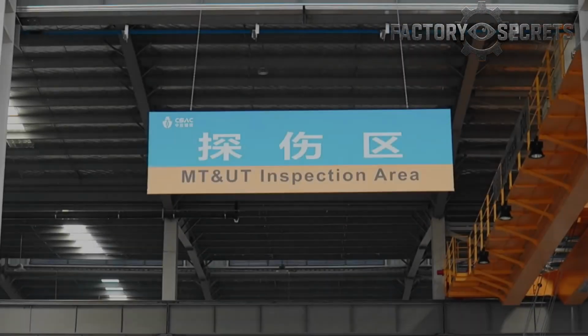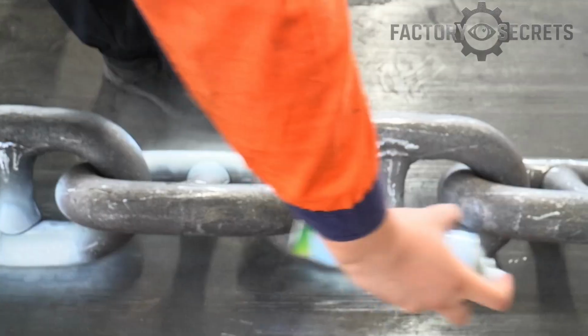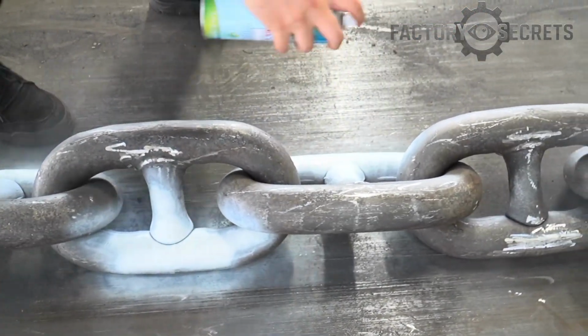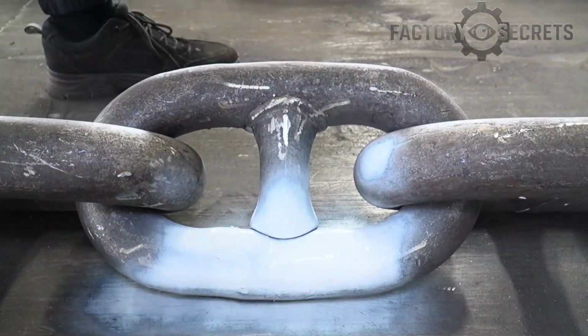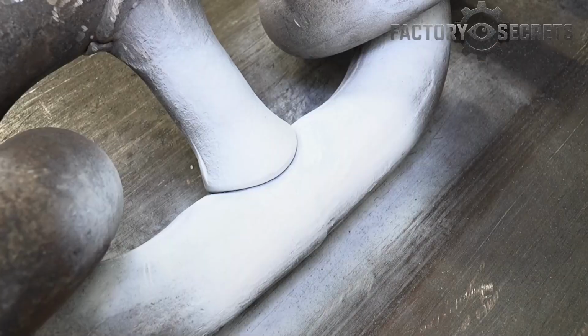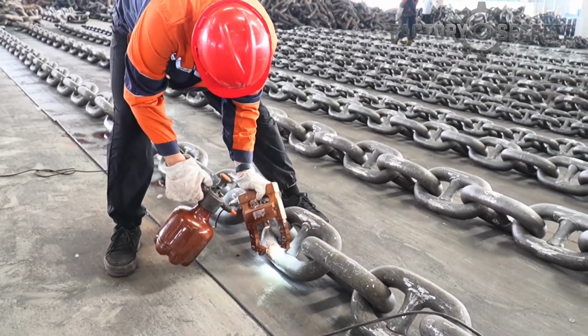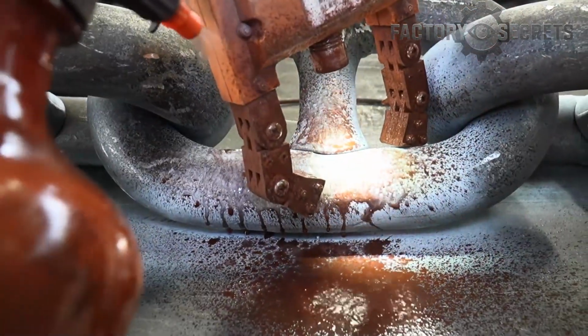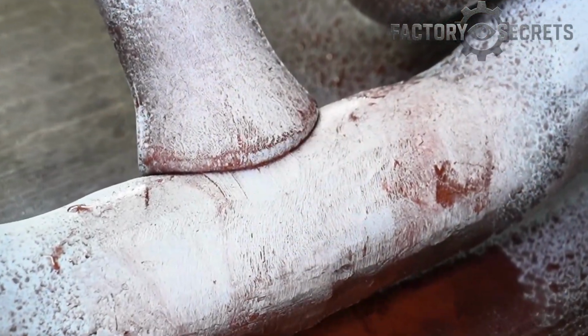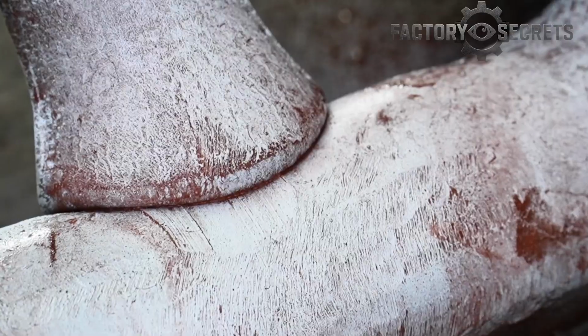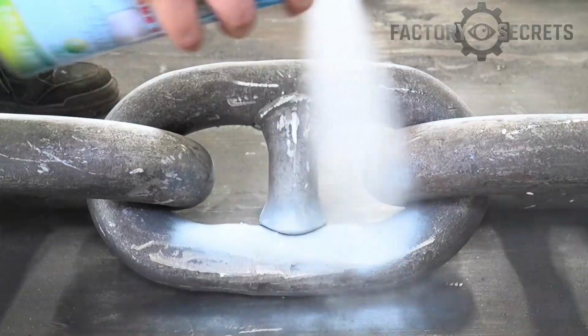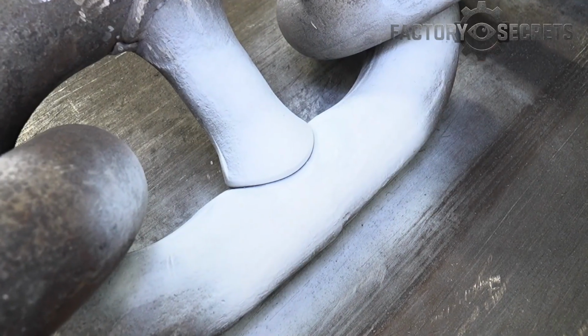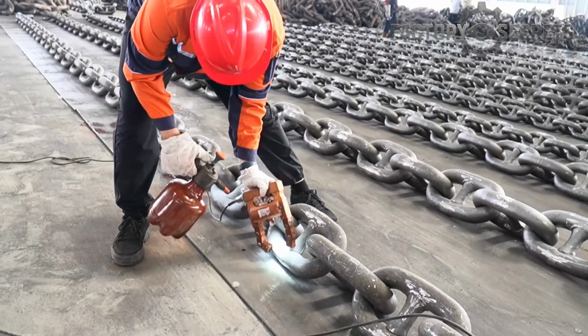Now we enter the world of non-destructive testing, and this is where the science gets fascinating. An inspector applies a white contrast spray to designated areas of the chain. Then a brown magnetic particle solution is applied directly on top. This is magnetic particle testing, or MT, a method for detecting surface and near-surface defects that are completely invisible to the naked eye. When a magnetic field is induced through the steel, any cracks or discontinuities in the metal will disrupt that field and cause the magnetic particles to cluster at the defect site. The contrast medium makes those clusters visible.